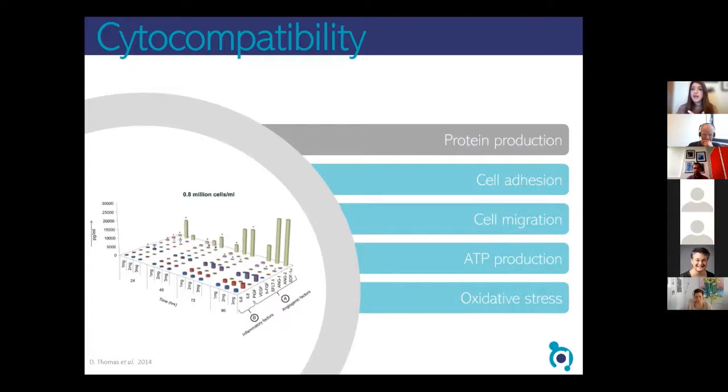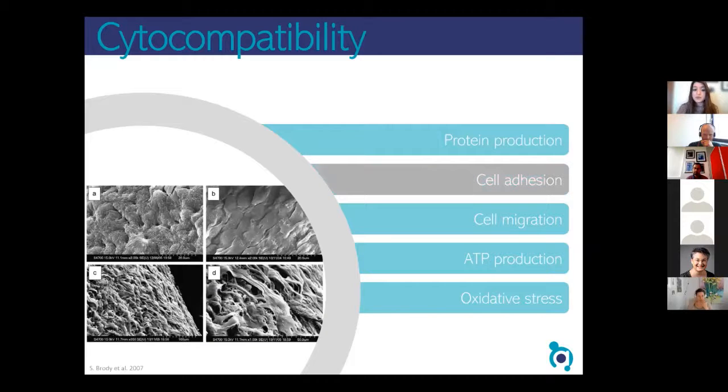So for instance, if we're interested in looking at the secretome, here it was a biomaterial that was designed to encapsulate MSCs. It was an HA, a collagen hydrogel encapsulating MSCs, designed to see if it could actually promote angiogenesis. And here you can see that the fact that the cells were encapsulated inside of them, the MSCs were producing a lot more angiogenic factors. So maybe you're interested in seeing if you're actually promoting that aspect. So you would go for ELISAs or proteomics, etc.